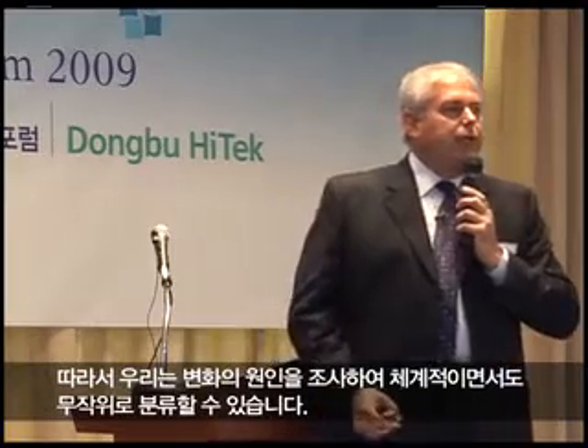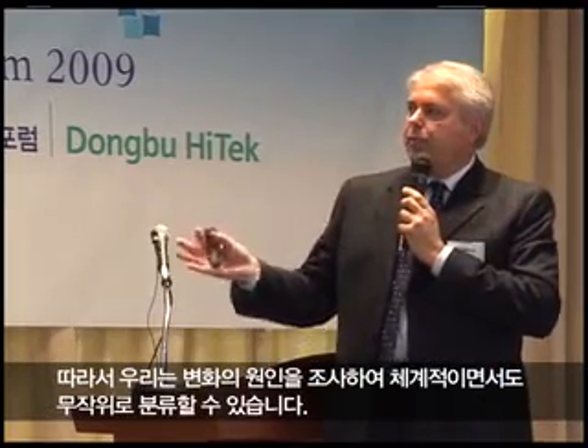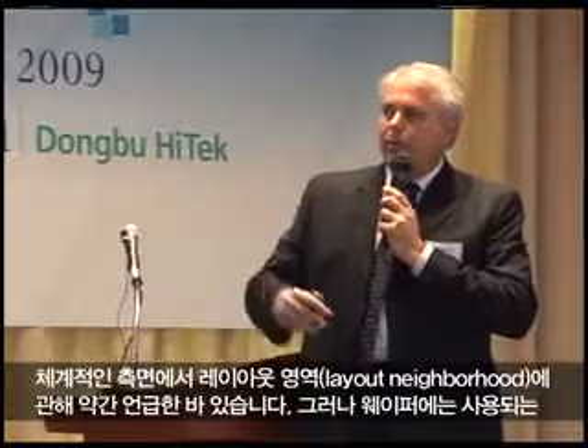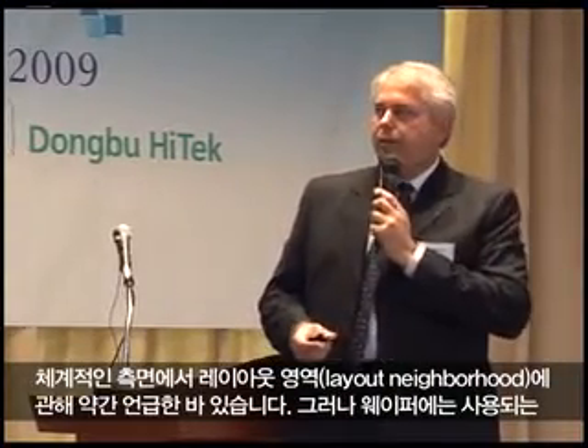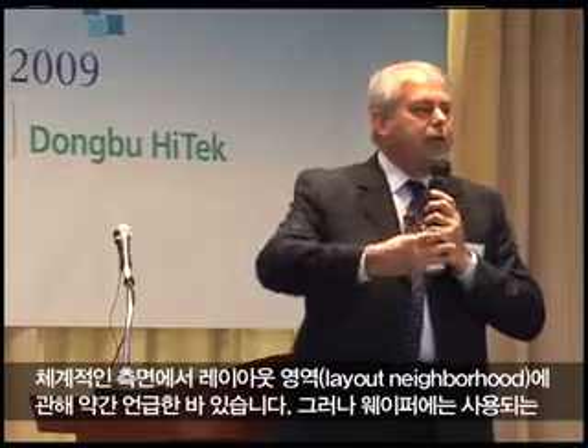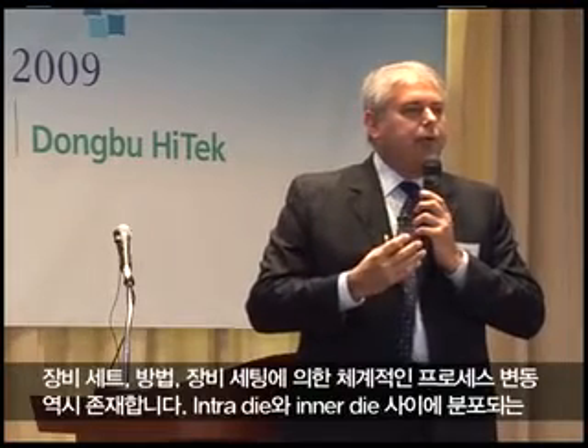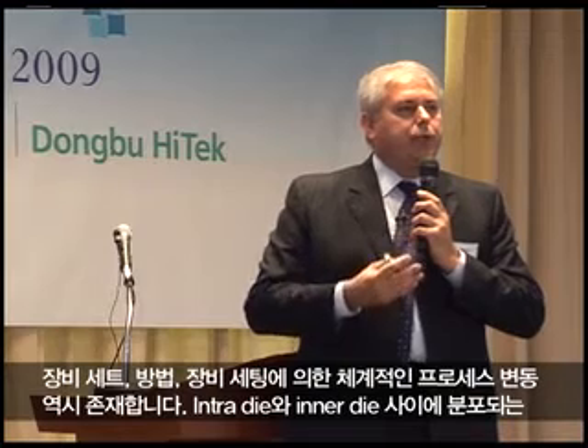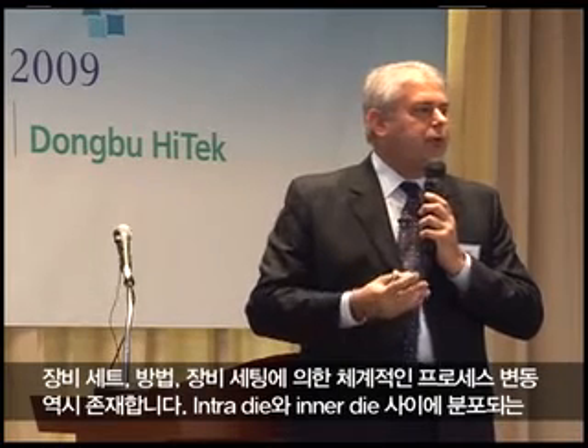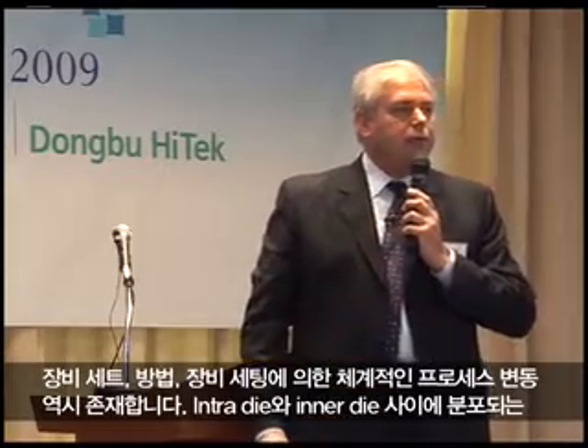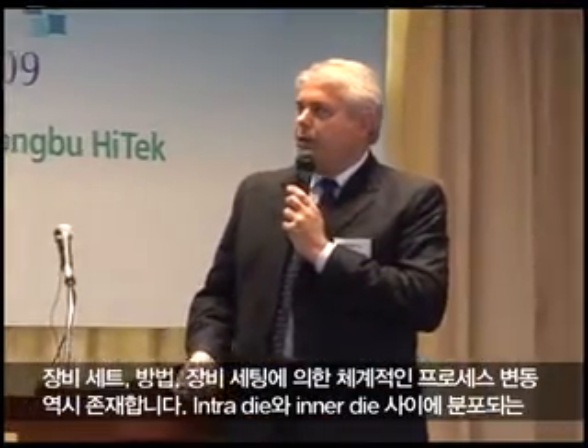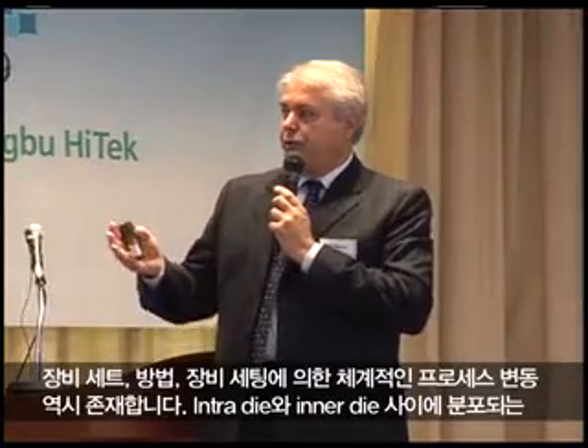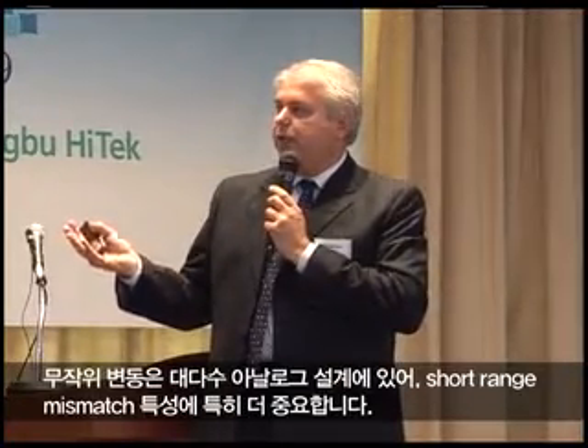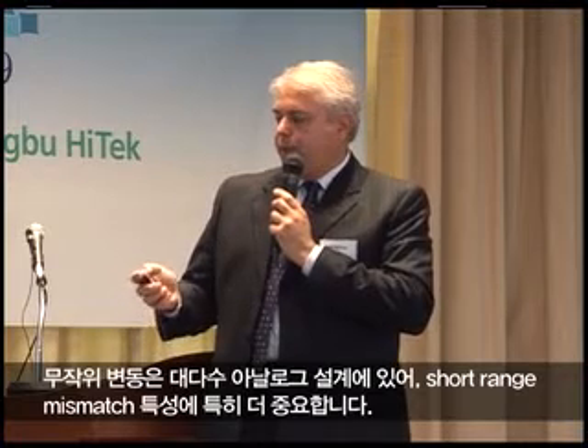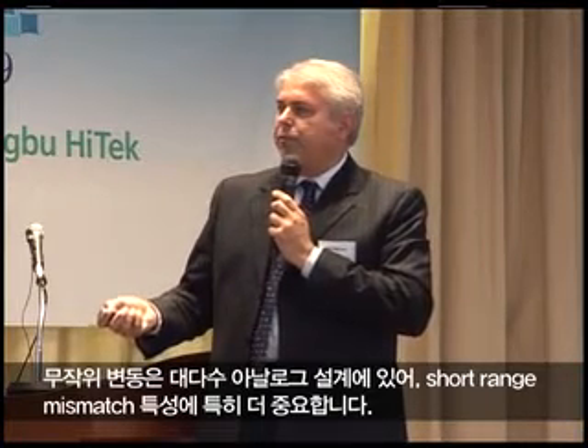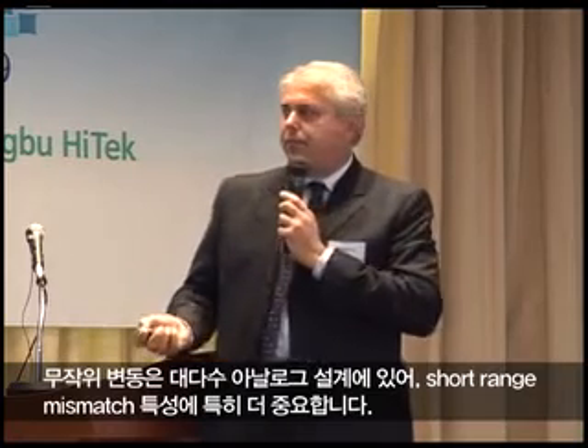So we can go through and classify the sources of variation into systematic and random. We spoke a little bit about the layout and neighborhood on the systematic side, but there are also systematic process variations across the wafer that are induced by the particular equipment that is used, or the particular recipes or particular settings of that equipment within the recipe. The random variations are distributed between intra-die and inter-die. And the ones that are particularly important to us are short-range mismatch in many analog designs.